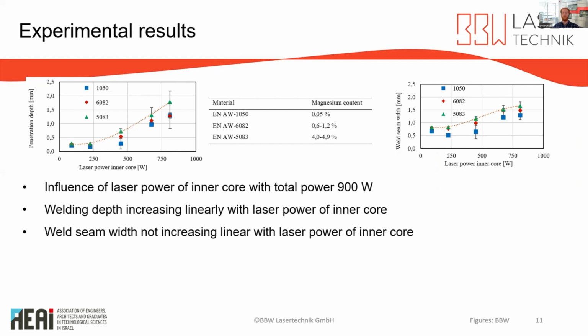In order to determine the influence of power distribution of inner core and outer ring on penetration depth and weld seam width, the power distribution is varied while the total laser power is kept constant at 900 watt. The results for penetration depth are displayed in the left figure.